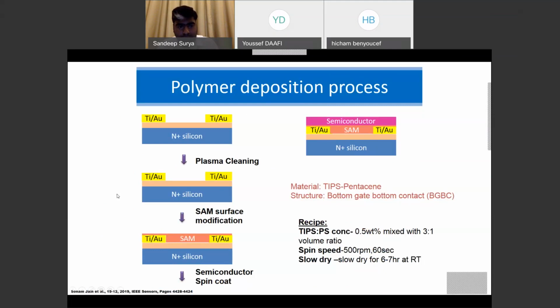So the process involves plasma ashing to clean. This is more or less like cleaning with a wet process also. And then we deposit SAM layers, which are self-assembled monolayers that play a very good role in adhering the organic semiconductor to the dielectric present in the bottom. And then finally, we have realized the TIPS-Pentacene on the top. As I told you, this is a bottom gate, bottom contact structure. The process recipe is shown over here.